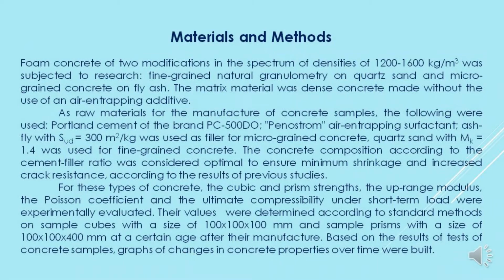Foam concrete of two modifications in the spectrum of densities of 1200 to 1600 kg/m3 was subjected to research: fine-grained, on natural granulometry quartz sand, and micro-grained concrete on fly ash. The matrix material was dense concrete made without the use of an air entraining additive. For these types of concrete, the cubic and prism strengths, the modulus of elasticity, the Poisson coefficient and the ultimate compressibility under short-term load were experimentally evaluated.